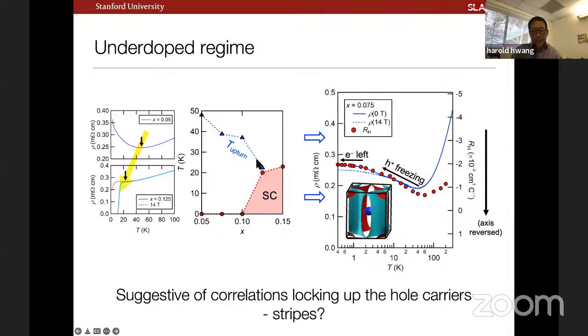What we found was actually kind of interesting: if we look at the Hall coefficient in detail, here I just show an example for 7.5% doping. This is the same resistivity on a log temperature scale. This is the upturn. If I plot the Hall coefficient, flipping it over here, this really tracks it one for one as we go to this low temperature regime.